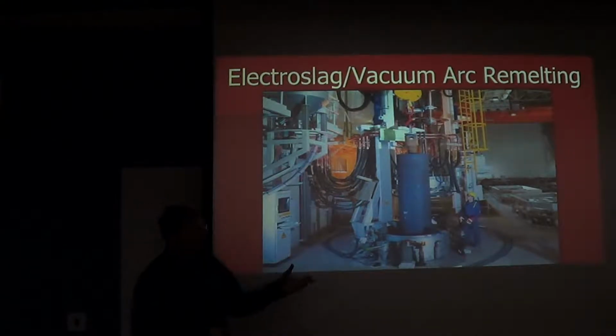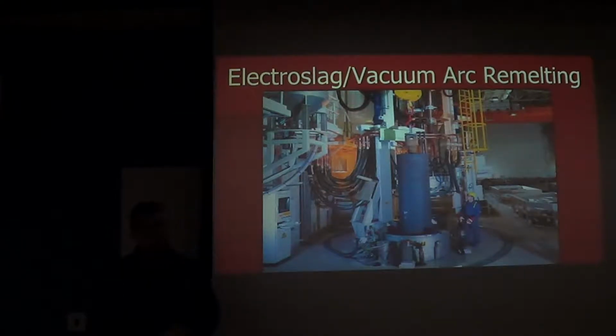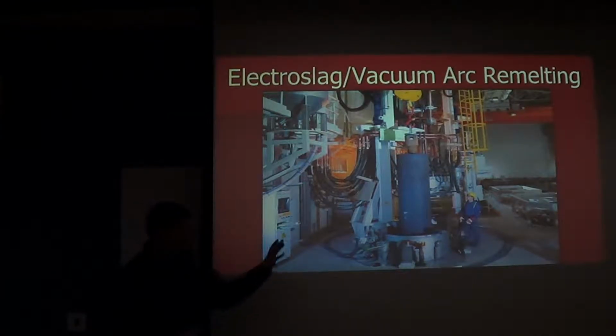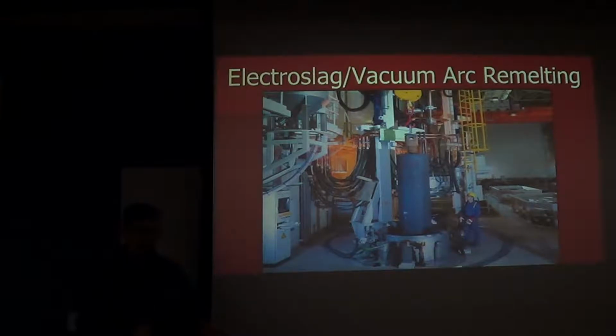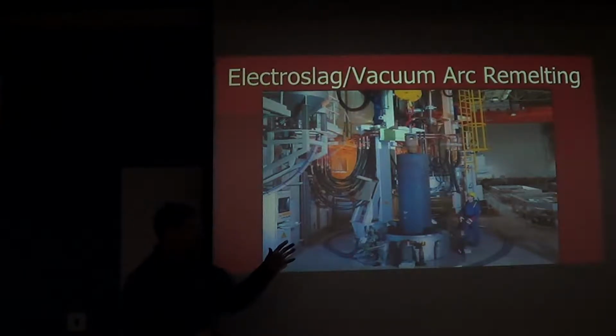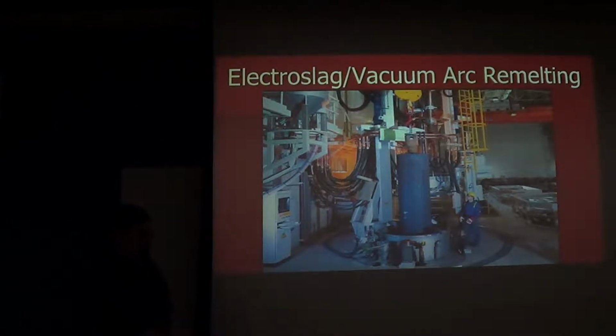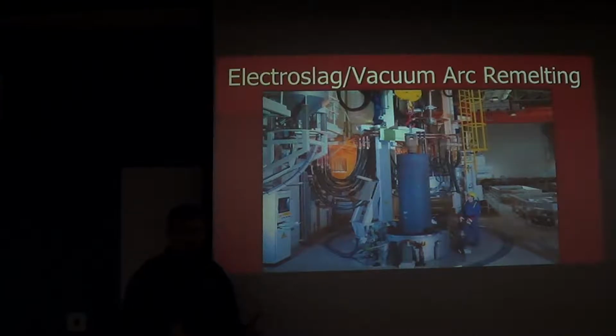There's a variation on this method that's called the vacuum arc remelting process. The setup is basically the same, except that rather than using a slag layer, the melting process is done under vacuum. That process is ideally suited to removing any extra dissolved gases that you may have picked up.